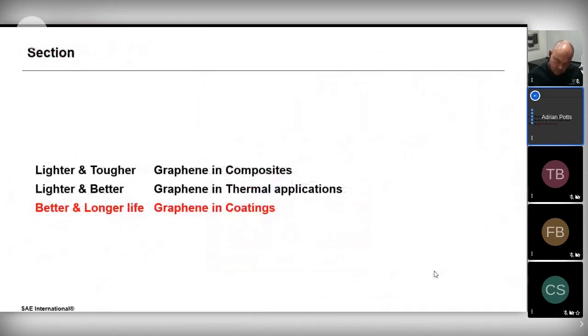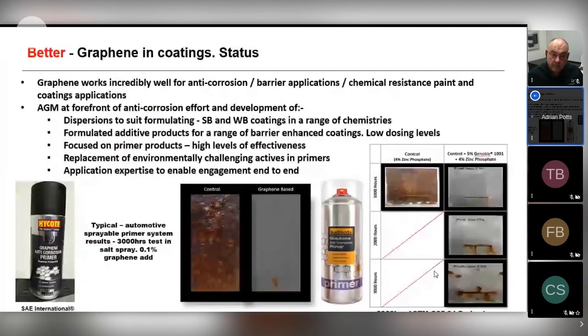And then thirdly, our third area, just as a brief overview, is in the area of coatings. At AGM, we believe we've done all the hard miles in this area in terms of graphene application and graphene dispersions that are now pretty much optimized for paints and coatings. Our area of excellence is principally in primer applications and both solvent and water-based systems. Graphene works incredibly well when formulated in the correct way for anti-corrosion, for barrier applications, for chemical resistance, for paints and coatings. I mentioned primer is our key area of activity, but when we look at tie coats and top coats also, clearly the materials can be integrated into those systems as well.